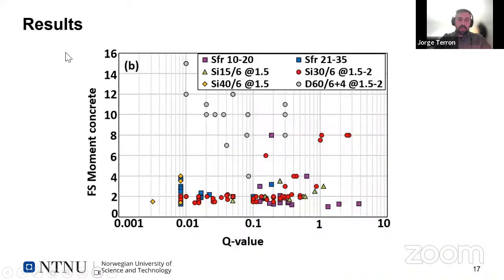If we put the previous results also in terms of loading on the support, in this case the factor of safety for the moment in the shotcrete support as a function of the Q value on the x-axis, we see for all of the colored dots, except for the gray ones, that a factor of safety between 1.5 and 2, which is quite reasonable for tunnel engineering, is obtained for Q values below 0.1. But above 0.1, we start seeing some spread. For us that is telling that the Q system is working reasonably okay for Q values below 0.1, but above that, we have this transition zone that I mentioned before, where we need other types of approaches.